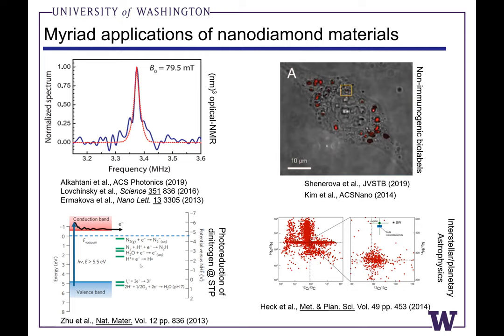Also, point defects in diamond have been used for photocatalysis. This is a really nice paper from the Hammers group in Wisconsin, effectively showing the reduction of N2 molecules to ammonia near standard conditions. The promise is that you could potentially bypass the Haber-Bosch process that consumes 2% of global energy supplies just to make ammonia for fertilizers. And these point defects could potentially be used to generate photoelectrons that could fix N2 to ammonia without having to go through the extreme temperature and pressure conditions used in the Haber-Bosch process.